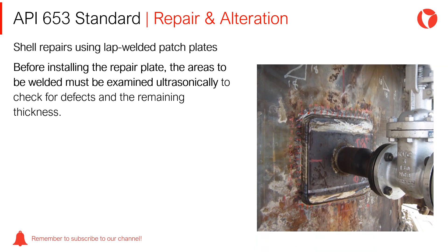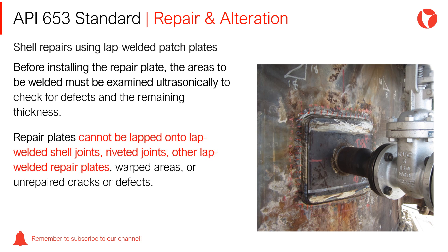Before installing the repair plate, the areas to be welded must be examined ultrasonically to check for defects and the remaining thickness. Repair plates cannot be lapped onto lap-welded shell joints, riveted joints, other lap-welded repair plates, warped areas, or unrepaired cracks or defects.